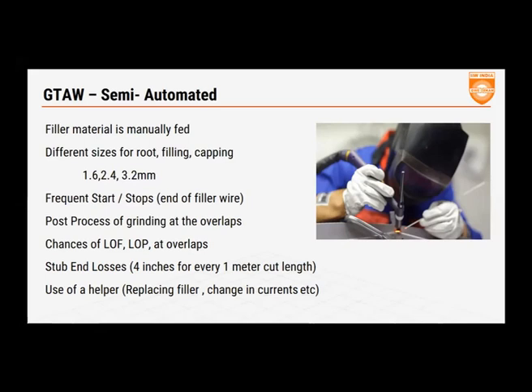Once that cut length is over, again he has to stop, which leads to a lot of post-process grinding as there are overlaps. Each time you stop and start, that overlap part will have a little high point. You would have to grind it off. And chances of lack of fusion, lack of penetration at overlaps are highest because whether the upslope, downslope was matched properly, whether the enough fusion had happened at that time. Again, stub end losses, very critical. Your typical cut lengths are 1 meter. If you look at last 4 inches that the operator cannot reach closer enough, he has to throw them away, which means about 100 millimeters for every meter. That's close to 10% of your raw material purchased, consumable purchase is gone in scrap. Also, this needs a helper.